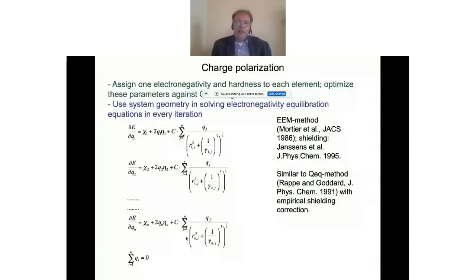We take the derivatives and optimize the charges based on this. That is a relatively expensive step because we have to solve essentially an N-by-N matrix. But with some computational tricks, we can make that almost go linear with time. This is still the step in ReaxFF that takes the most computational expense for large systems. Every iteration we update the charges, and that gives us a reasonable physical response, especially when the chemical environment changes. For example, a carbon atom going from an oxygen-rich to a hydrogen-rich environment changes its charges automatically, and so that allows us to take that sort of chemical change into consideration.